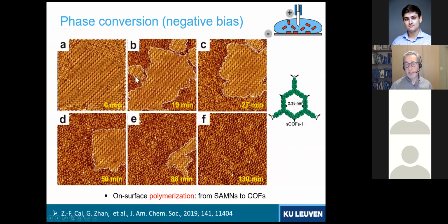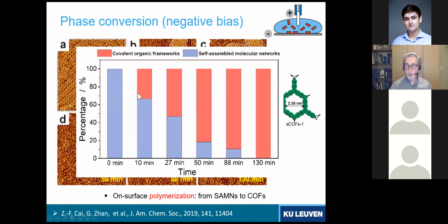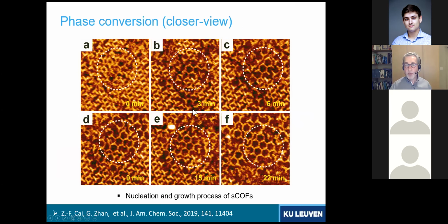This is then the same molecular system where we start from the self-assembled molecular network and where we change the bias to negative bias. And in time, we see that the original self-assembled molecular network, supramolecular network, disappears and is replaced by the covalent organic framework. And we can follow this, of course, more in a quantitative fashion as a function of time. And we can even